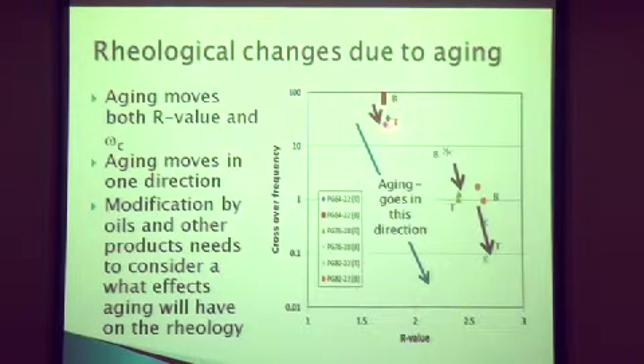Here I show some cores from Newark. Newark Airport is the airport I fly out of to come here. New York City. This shows some cores taken from this. This was that PG 64-22 material, not cracked. These were polymer modified materials. These were the materials that they thought they were applying extra quality with, for more aging. When we plotted these using the Glover-Rowe parameter, they crossed that line in the Glover-Rowe parameter.